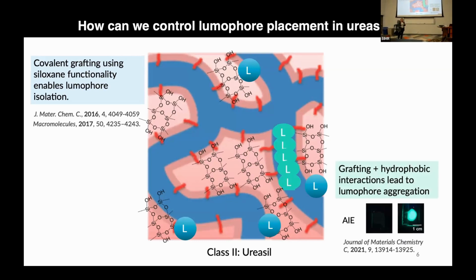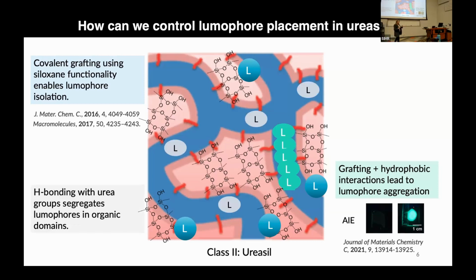Alternatively, we might have a really hydrophobic species that prefers to reside in the organic domains. And so in this case, this is an example where we use a lumophore that's an aggregation-induced emitter. And we force aggregation within the organic domains. And in this type of luminescent species, that actually switches on the luminescence. So the aggregation promoted by the host matrix switches on the luminescence. We can also, and this is something we're looking at the moment, exploit the urea groups and use interactions via the urea groups as an alternative method to place our lumophores in the matrix.